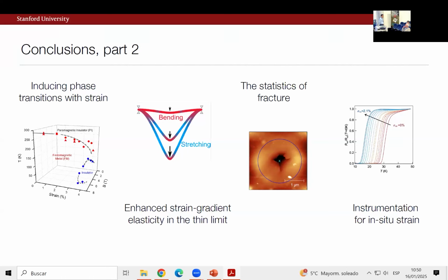So in this case, when you are stretching, for example, you put 8 or 10 unit cells of membrane. Do you think the first layer, which is just on top of the polymer, is facing the same amount of strain, because you are calculating the strain percentage according to your Kapton one? There could be a strain gradient, and do you think that could play a role? Yeah, that's not a silly question at all. Indeed, conceptually, this is quite possible.